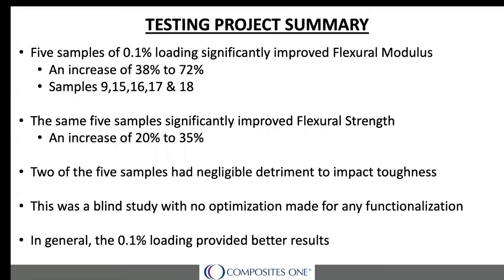So, 5 samples at 0.1% loading showed significant improvement in flexural modulus and strength. Out of those 5 samples, 2 had negligible impact on the toughness of the resin. Now, I want to reinforce that this was a blind study, so there was no bias given to any graphene supplier. However, that also means that we could not optimize for any type of functionalization the suppliers may have done. And as we mentioned, in general, the 0.1% loading provided better results.